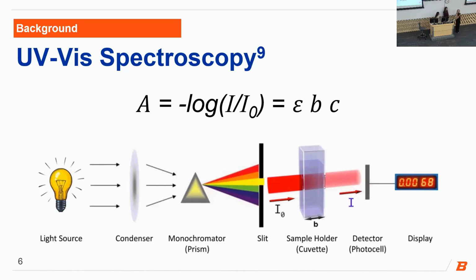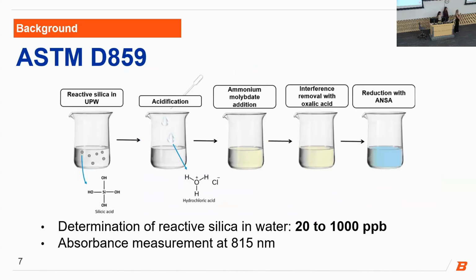This means that higher silica concentrations will produce higher absorbance values. The way it works is light at specific wavelengths is transmitted through a sample, as shown in the diagram there. And then our detector takes intensity measurements of our I naught and I terms, which we can then use to calculate the silica concentration in our solution. It is important to note that the detector does only measure light intensity, and it is agnostic to scattering and refraction, which can influence our measurement readings. This becomes especially important later when we discuss sources of measurement variability in our results section.